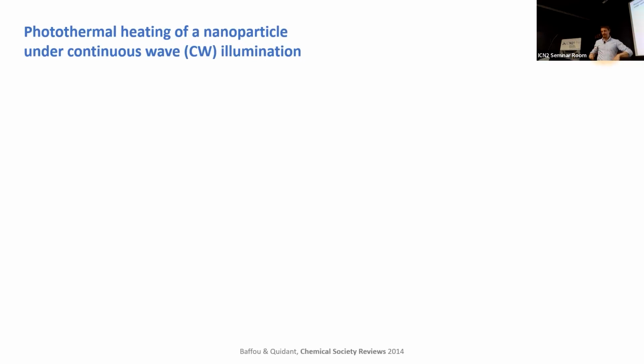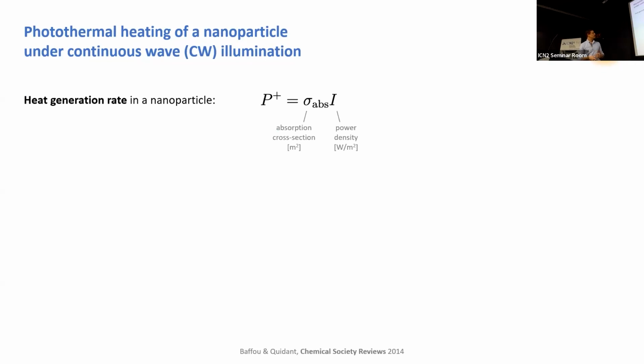Okay, if we think about it, let's say we have a piece of glass, and we have a nanoparticle sitting on top, and now we shine a laser onto it. There are two things that happen. The nanoparticle will absorb light and will heat up. And the rate of heating will be given by the absorption cross-section, which, if you remember, is an area, times the power density, which is watts per unit area. So the multiplication of the two is simply watts, or joules per second. That's how much heat we are creating in a nanoparticle for any given second, right? And it's called the heat generation rate.